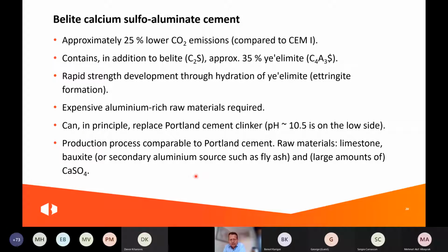Sometimes, depending on the type of product, a secondary material can be used, like fly ash. But often you need this pure bauxite as raw material, and that is expensive. And if you want to replace the whole volume of Portland cement, of course, you will run out of this bauxite in the longer term. But interesting, in principle, it can replace Portland cement clinker.